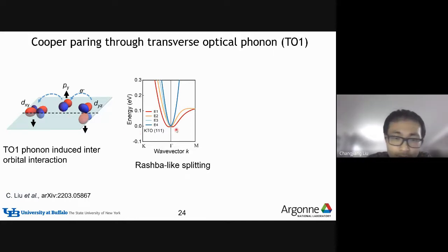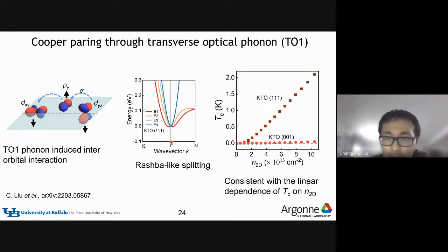Because of this transverse optical phonon, we found that the electronic structure is modified, and there is a Rashba-like splitting at the KTO 111 interface. And in particular, we found that using this coupling, we can reproduce the linear dependence of Tc on carrier density. At the same time, the Tc on the KTO 001 surface is vanishingly small, which is consistent with what we found experimentally.